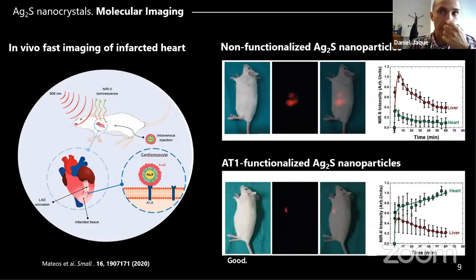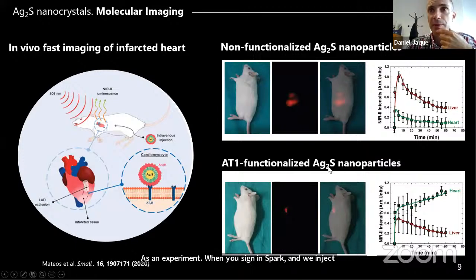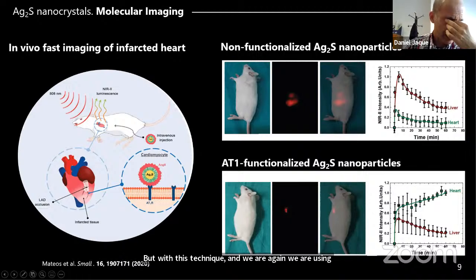Okay, if we repeat the same experiment, we induce an infarct and we inject these AT1R functionalized silver sulfide nanoparticles, what happens is that the nanoparticles are accumulated at the heart of the animal due to the presence of the infarct. So with this technique, we are using only light, we are using diode light for excitation, and we are using the luminescence of the nanoparticles for image reconstruction. And you can see that we can get a clear image of the infarct using this functionalized nanoparticle.